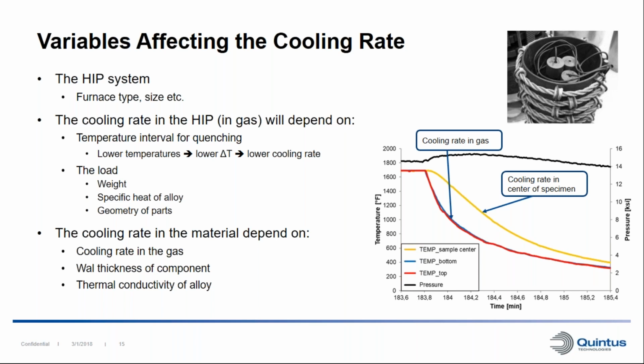For example, a thicker, bulkier part would have a slower cooling rate in the center. Also, the thermal conductivity of the alloy will have an influence. How fast can we transport heat within the component? If we look on the right here again, we can see a cooling curve. So these curves are from thermocouples in the gas, and this thermocouple is measuring inside the specimen, corresponding to this picture on the top here.